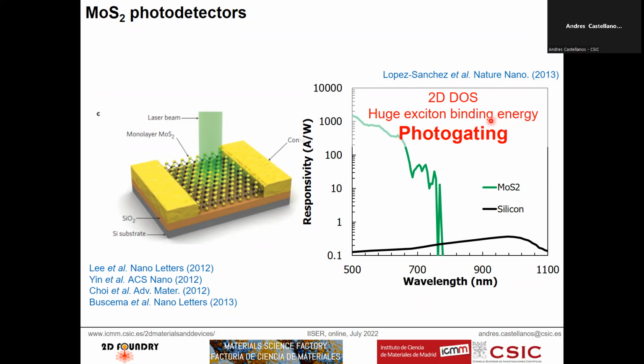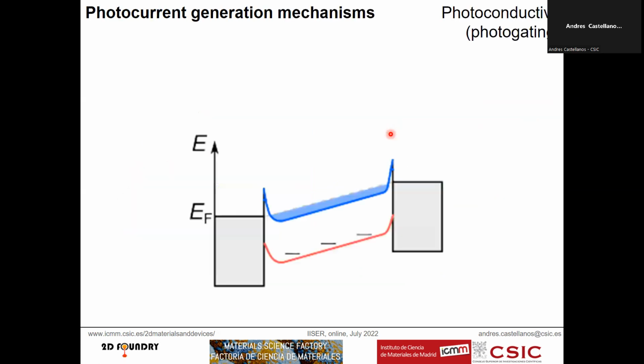But probably one of the main reasons why these materials have this large responsivity is because, as they are two-dimensional materials, they are very sensitive to trap states, and therefore they are eligible to present a mechanism of photocurrent generation that is called photogating. Okay, I'm going to briefly explain what this photogating mechanism is. That is basically a particular case of photoconductive effect.